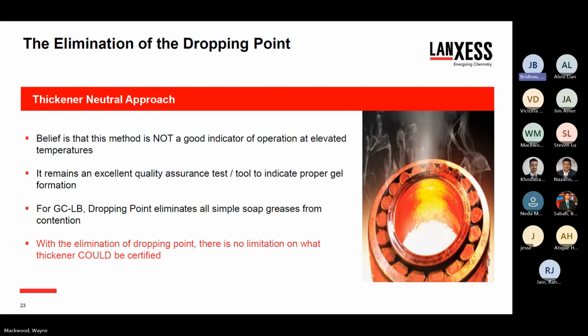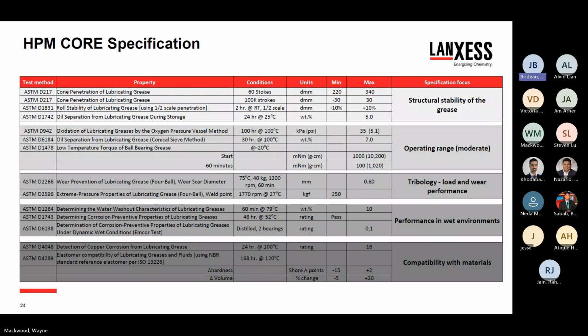And this is what the HPM specification looks like. This is called the core specification. All products have to pass this spec to be given the label of certified HPM core spec. We've broken it into five areas of focus. One is the structural stability of the grease. One is the operating range, which for the core specification is relatively moderate operating conditions. One area is tribology, that is, the load and wear performance. Another is wet environment performance, so corrosion and water resistance. And finally, compatibility with materials, including copper corrosion as well as elastomer.